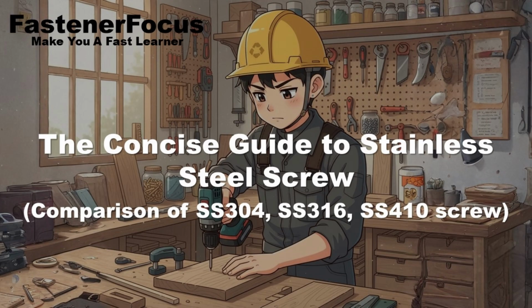Exactly. The less noble metal acts as the sacrificial anode and will corrode preferentially and rapidly to protect the noble stainless steel cathode. The corrosion rate of the active metal is dramatically accelerated, often far beyond what normal environmental exposure would cause. So, using a highly durable 316 stainless screw to attach a bracket made of standard aluminum to a boat hull, or even just outdoor aluminum siding in a wet environment, is actually signing the aluminum's death warrant. The aluminum will pit, dissolve, and fail prematurely just to keep the screw safe.